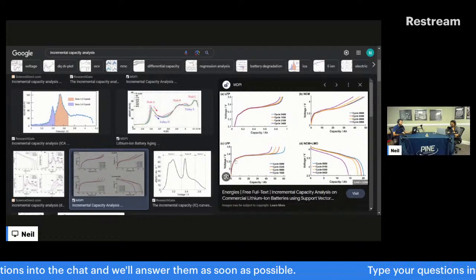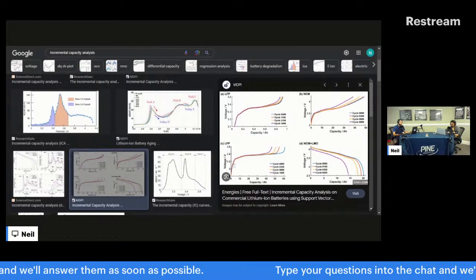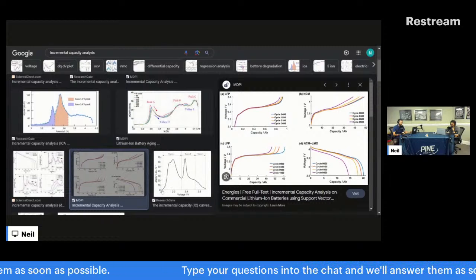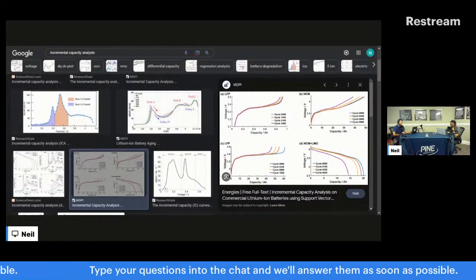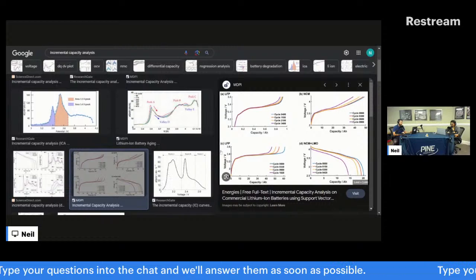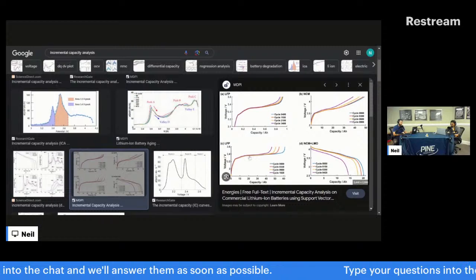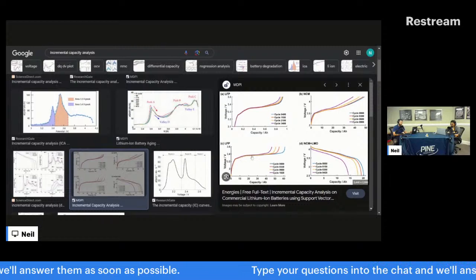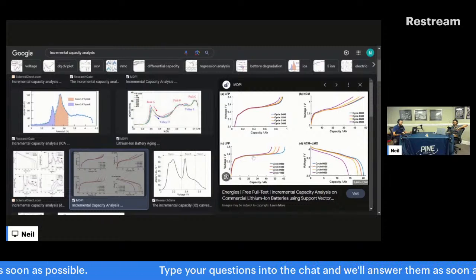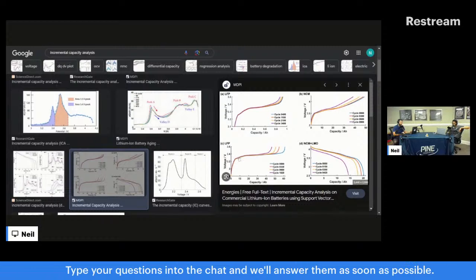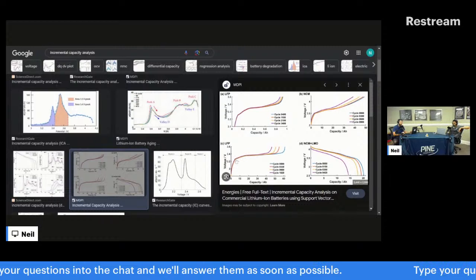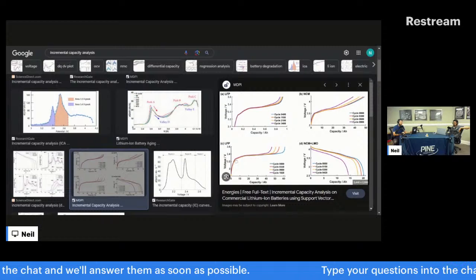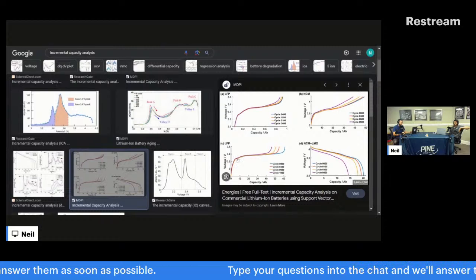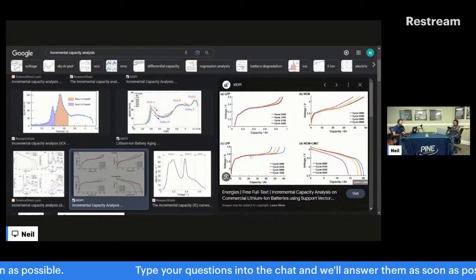So that's a low dQ. This is like before the first peak. Over here, for example, you see the start, I have no dQ/dV. Then I have a big peak because it's flat. The Q is changing as the x-axis goes out, but the voltage on the y-axis is relatively steady. Usually charge-discharge tests have something like one slope, and then it flattens to a different slope.